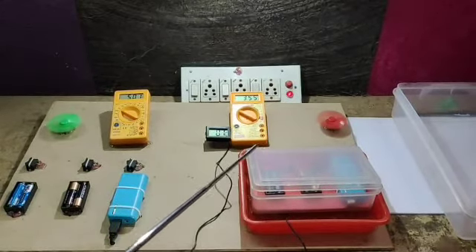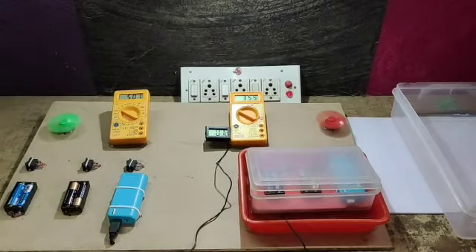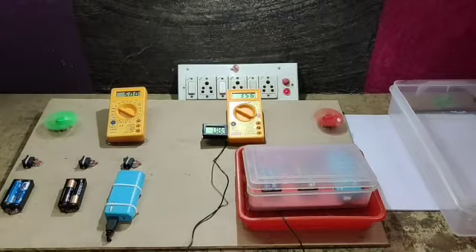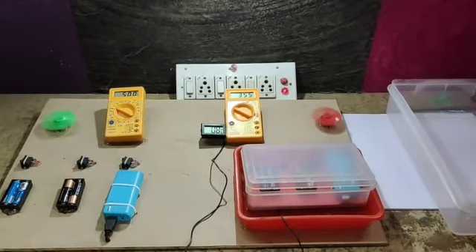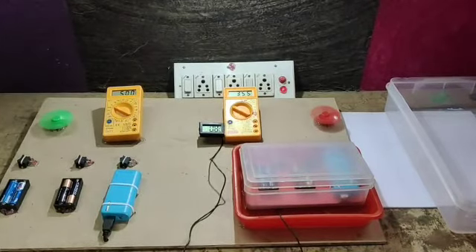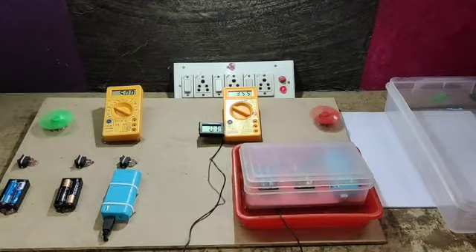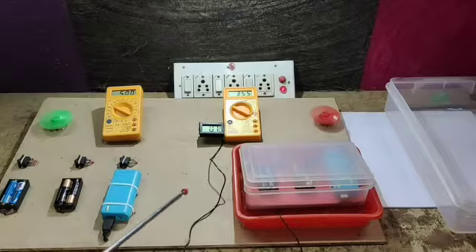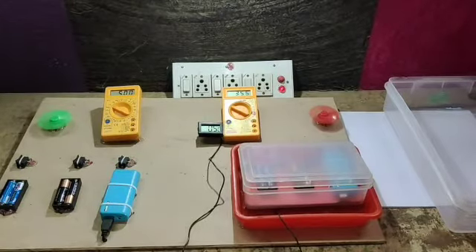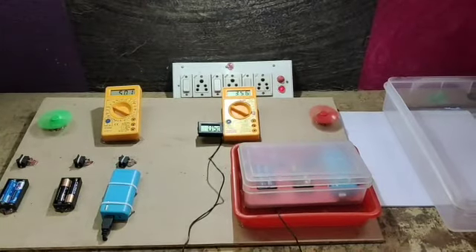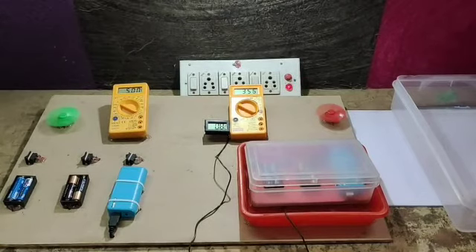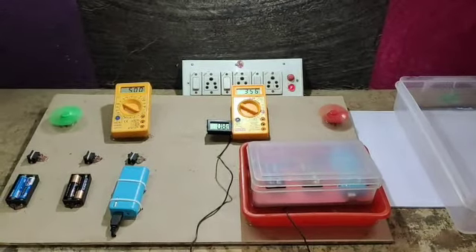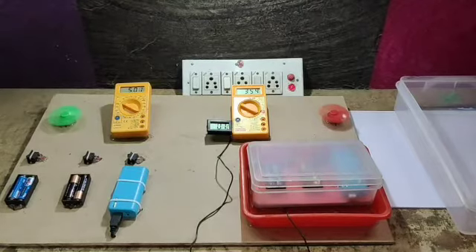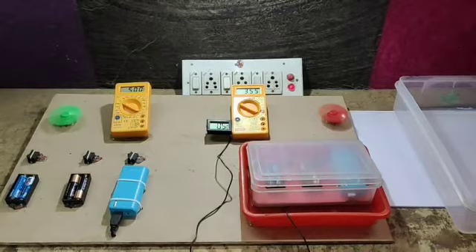So what we can finalize is that in cold temperature the voltage reduces by 20 to 25%. Generally lithium batteries work better at 20 degrees centigrade to 40 degrees centigrade. And once the temperature decreases, the voltage decreases. So in normal temperature, the voltage remains the same, and in cold temperature the voltage reduces by 20%. In lithium batteries, what we can decide is that they work better at 20 to 40 degrees centigrade, and the voltage reduces as the temperature goes low.